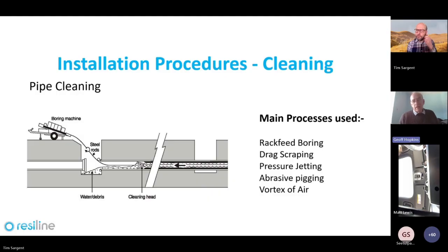So rack feed boring is a good technique for pipes that have heavy encrustation. If you travel around the world, you'll find that people don't tend to have rack feed borers sat in their yards or anything. So drag scraping, where you can use a couple of winches, is far more common, as well as pressure jetting. Most countries obviously will be able to undertake those techniques with locally obtained equipment. Abrasive pigging and the vortex of air, or air-driven aggregate really, which is blown through the pipe. The aggregate's blown through to knock the encrustation off the insides of the pipe.